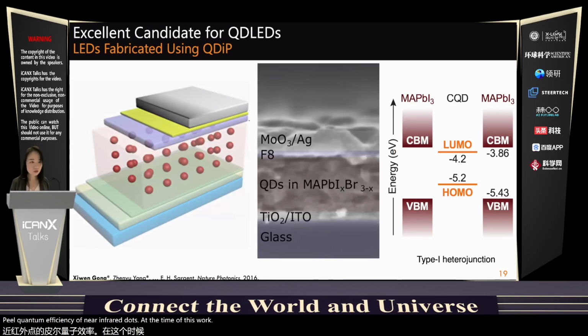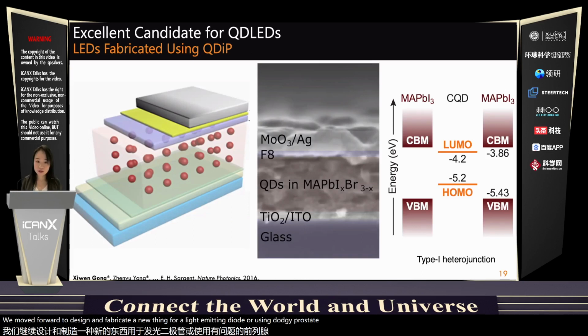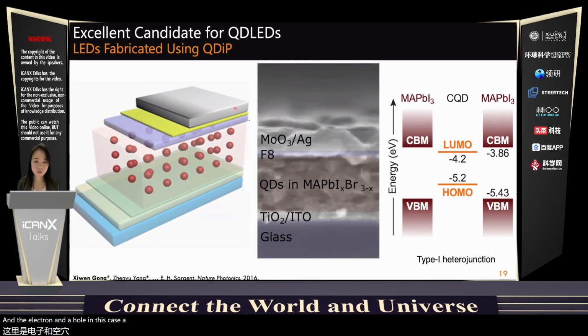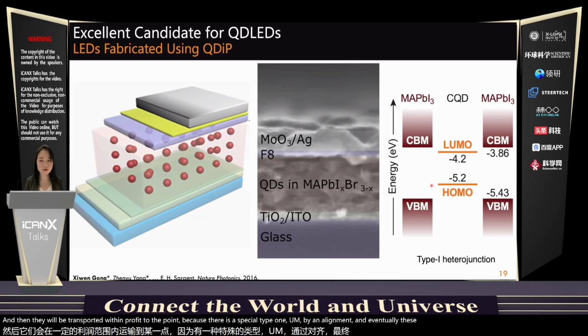So inspired by this excellent emission property and high carrier transport efficiency, we moved forward to design and fabricate a near-infrared light emitting diode using dot-in-perovskite. The electron and hole, in this case, will be injected from top and bottom electrodes into perovskite, this semi-transparent matrix here. And then they will be transported within perovskite to the quantum dots because there's a special type 1 band alignment. And eventually, these carriers will arrive at the dots where they recombine and emit light.